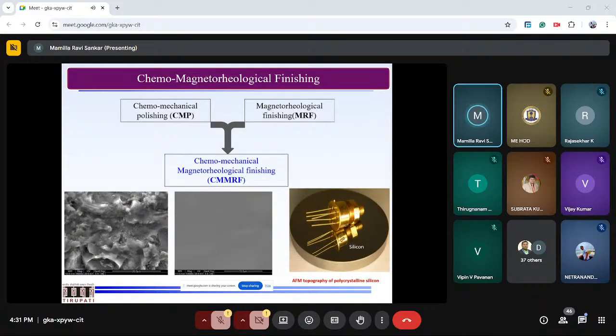As it progresses, you can play with the electromagnet and change to 0.5 Tesla, 0.25 Tesla, or 0.6 or 0.3 Tesla. So the strength of the magnetic field intensity for the CIP chains lessens as the surface finish increases, or, say, as the surface roughness decreases. You don't require high indentation values and so on. Initially you just go with 1 Tesla, where your chains are much stronger, so the abrasive particles have more support from the CIP particles.